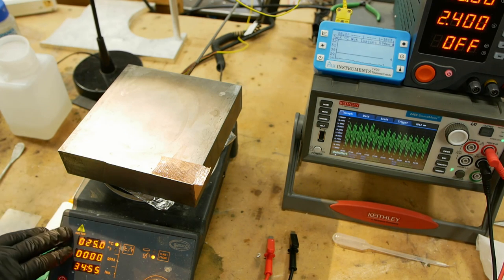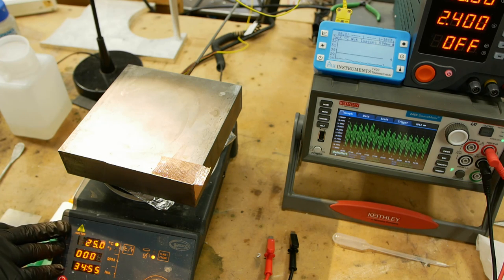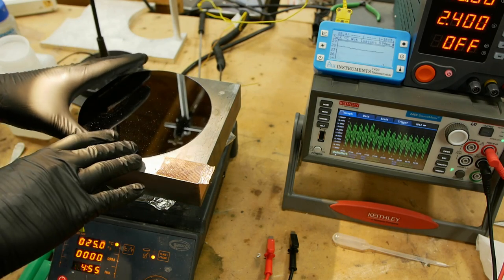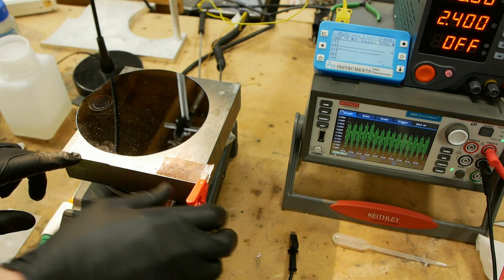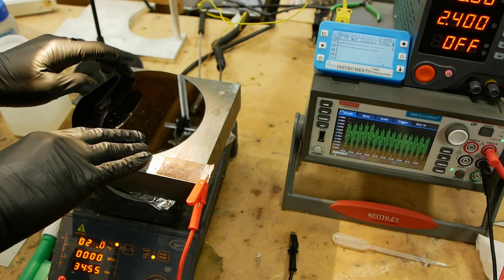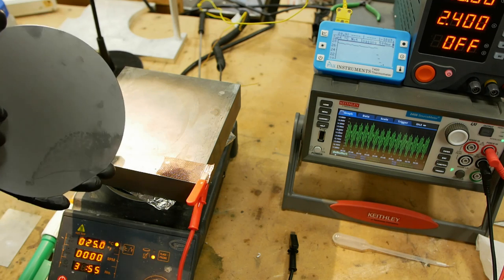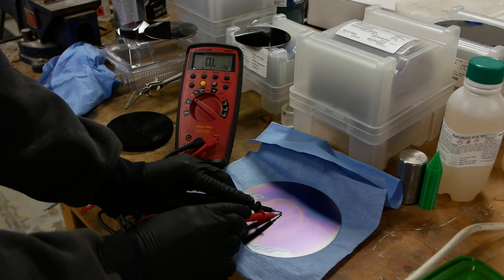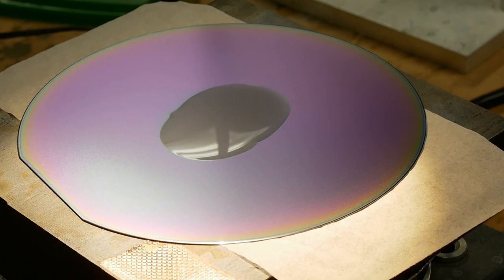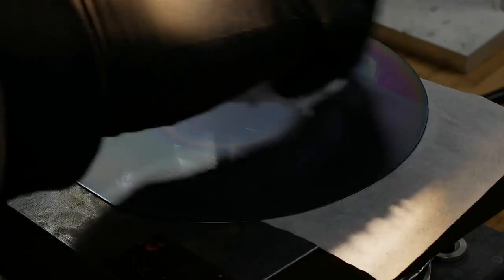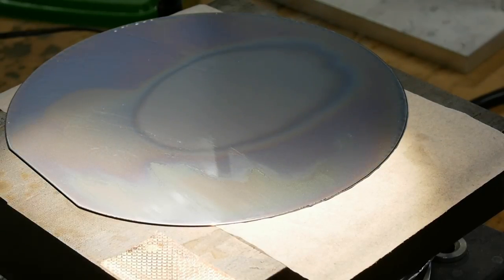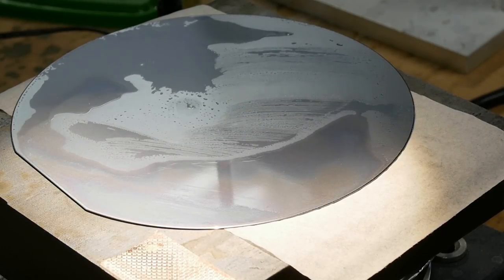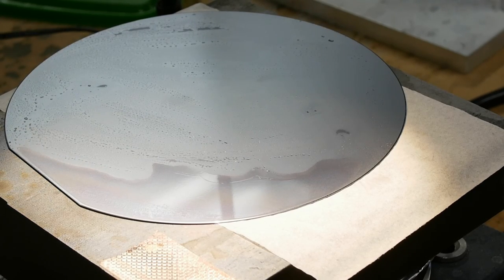Here's the setup that ended up working pretty well for me. The hot plate isn't really necessary, but it's just so cold out here in my shop that I need the hot plate to get back up the room temperature for any sort of consistency. And then I've got a really heavy steel plate here on top of the hot plate. And so we put the wafer on top of that and connect the steel part to the positive part of the power supply. And we just rely on the physical contact of the wafer bottom with the plate to make contact. As it turns out, this particular variety of wafer that I bought came with an oxide coating on the backside. And I had to get rid of that because that was a really good insulator. And I found the best way to get rid of that coating was to just use the etchant that I used in this electrochemical process without any electricity. Just spread it on there and let it sit for a minute or two, and it actually blows away that oxide coating. And you can test this by just taking a digital multimeter and just sticking the probes on there. If you just, centimeter apart, you should be getting something like hundreds of ohms or less. If you get kilo-ohms or mega-ohms, there's an oxide coating that's blocking it for sure.